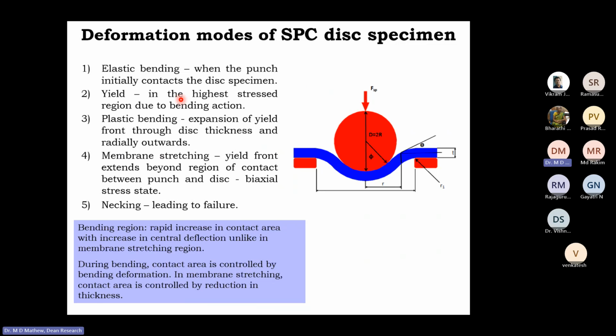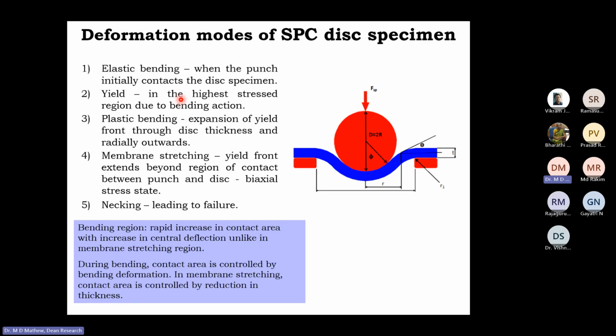So when the punch initially contacts the disc specimen, what happens is elastic bending. Slowly the yielding happens in the highest stressed region. That is the region at the root of the spherical ball. So that leads to plastic bending, and the plastic bending region expands. So the yield front expands through the thickness of the specimen and radially outwards. And the next stage is membrane stretching. That is when the yield front extends beyond the region of contact between the punch and the disc. And that region will be under a biaxial stress state. So this process continues with time, and finally there will be necking, and necking will result in failure.